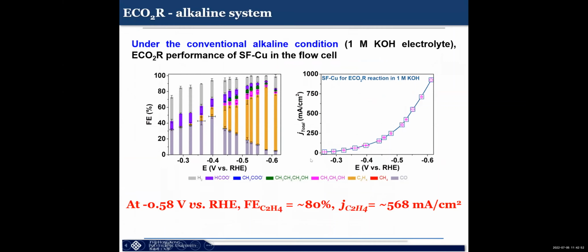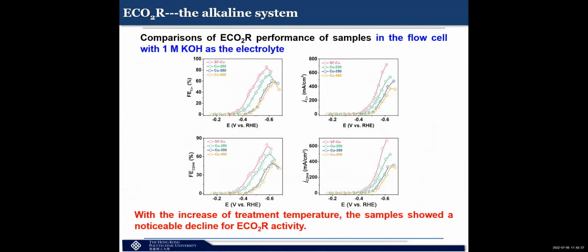1M KOH, typical standard process. So for our case, this material can already reach 80% Faraday efficiency at minus 0.58 volt, with quite high current density, 568 milliampere per square centimeter. So this result is already very encouraging. It's already compatible with most of the state-of-the-art copper material for C2H4. And then we looked at other annealed material.